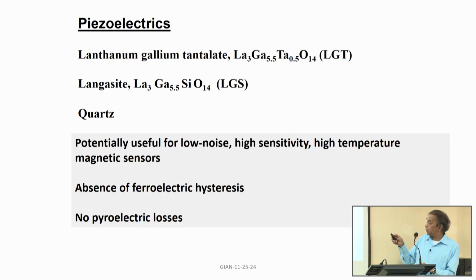And these are the piezoelectrics that we used in some of our studies. Lanthanum gallium tantalate, which is called langatate, LGT. Langasite is where the tantalum is replaced by silicon, that's LGS. You could also use quartz and also aluminum nitride. Gallium arsenide is a piezoelectric. People have used gallium arsenide and gallium nitride.